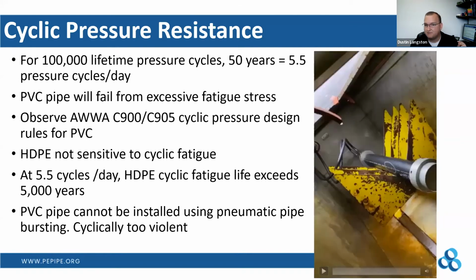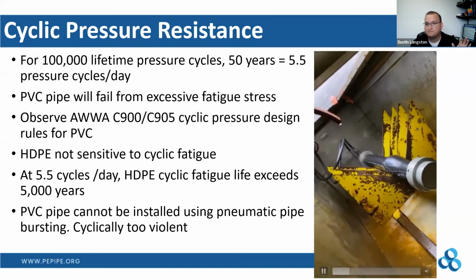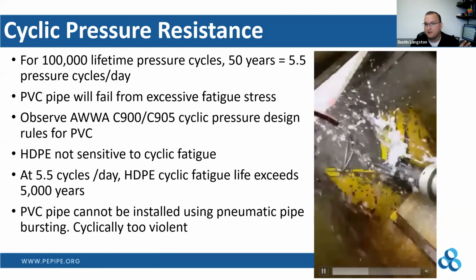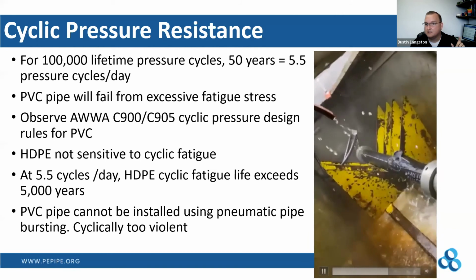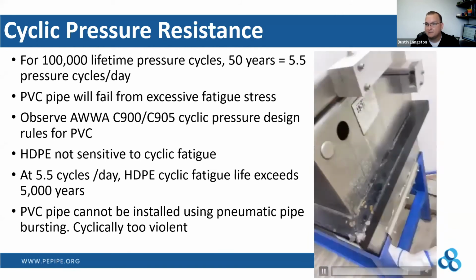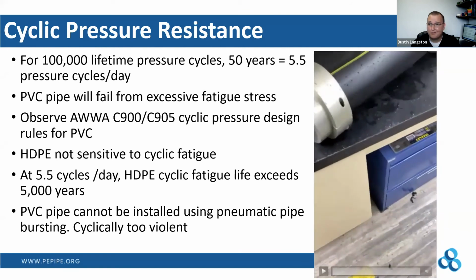But again, HDPE pipe, if you look at how this pipe is failing, it actually stretches to the point where it has thinned the wall and finally allows it to fail. Look at the expansion before the failure. The other thing I like to point out here is that failure is localized. We maybe lose a foot of pipe that has to be replaced, and you move on. The other thing I will mention is you are rarely going to see that scenario in the field. Alan hit it right on the head. We're talking 4 to 5 times the pressure rating of the pipe to actually blow it up. So the only time you run into that is if somebody's doing a pressure test on it and their gauge is broken or not calibrated, and they just keep putting more and more pressure, and it finally yields the pipe. So very, very rare that you'll ever see that type of failure in the field.